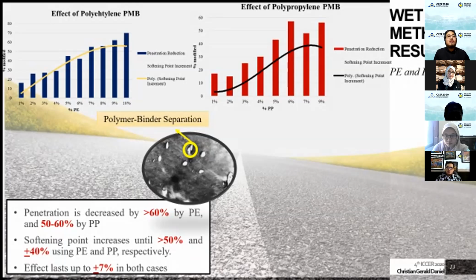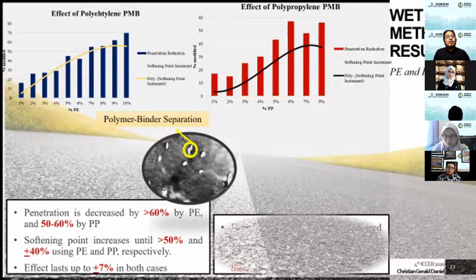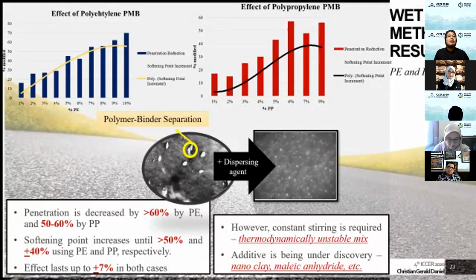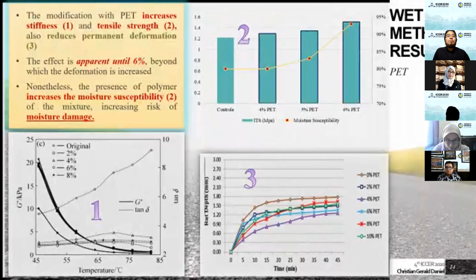That's why we need to stir it constantly. It is thermodynamically unstable, and it is kinetically stable if we stir it constantly. And to combat this, we have some additives such as nanoclay and maleic anhydride, which is a polymer also, etc. But it's still not an affordable method. That's why the price of the PMB product is significantly higher than its peers. What about PET? Basically, it is the same, with more stiffness and tensile strength and reduced permanent deformation, and the effect lasts until 6%. So it's quite the same, 6 and 7%, within PET, PE, or PP as well. And one more thing is there is an increase of moisture susceptibility for all the polymers, which indicates more risk of moisture damage.